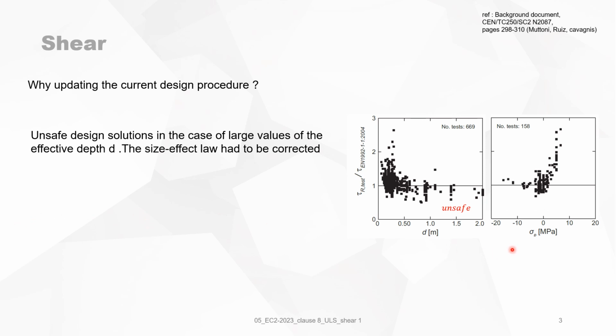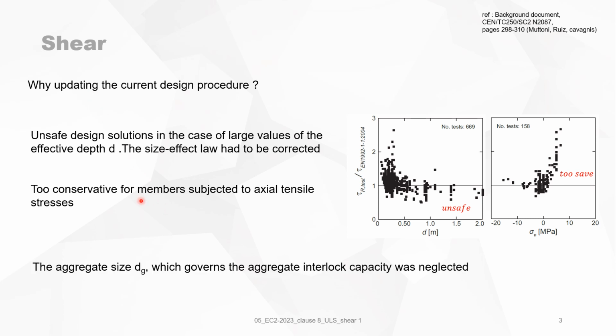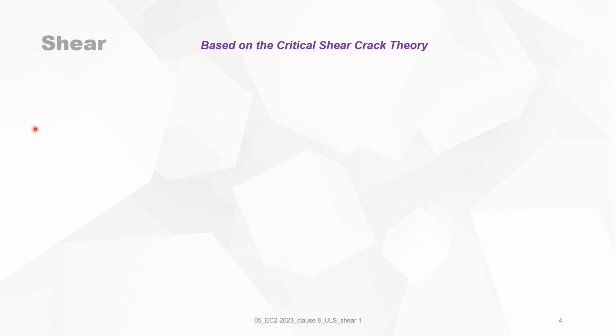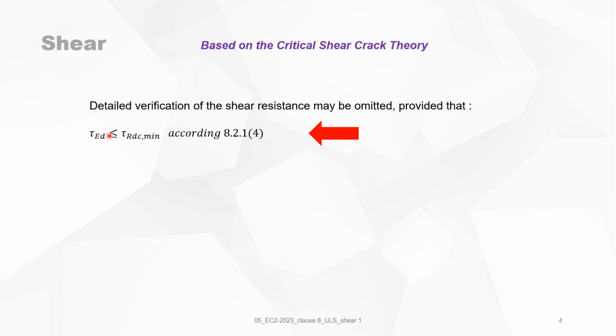On the other hand, when we have tensile forces, and you look again at the shear stress, you will see that this is too optimistic, it's too safe. So too conservative for members subjected to axial tensile stresses. So that's, in a quick way, to explain why we need an update of the current procedure. The aggregate size, dg, which governs the aggregate interlock capacity, was neglected in the 2004 code. So in the code of 2023, the shear resistance is based on the critical shear crack theory.